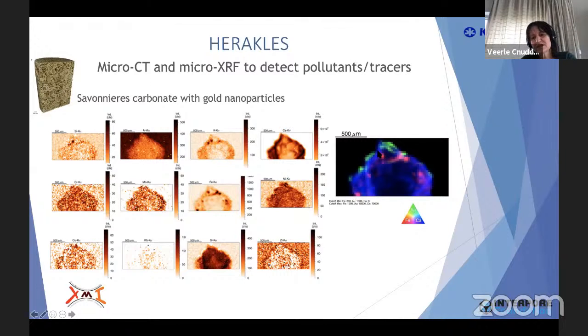In green, you see where the gold is present. For the rest, you see mainly calcite, which makes sense, and also some iron concentration. You also see that in the middle, no signal is picked up, and that is because XRF mainly works from the surface until something around, depending on the element you want to map, around 200 micron in depth. So it's not ideal, but it's a way to complement the CT data with chemical information.